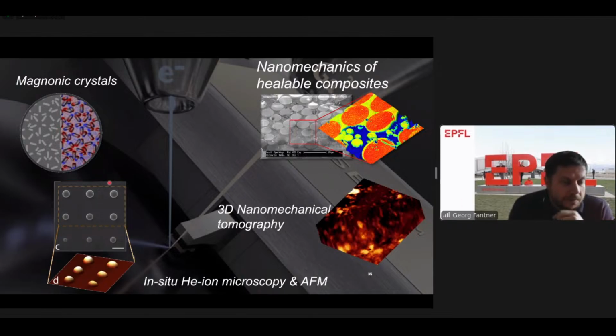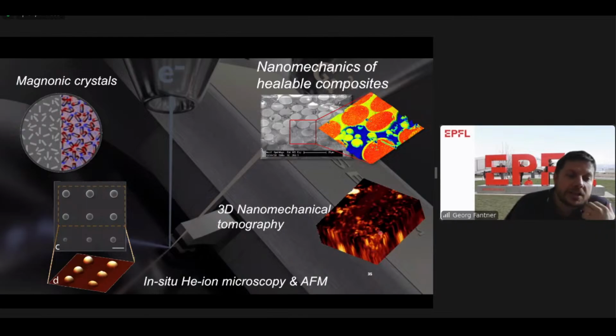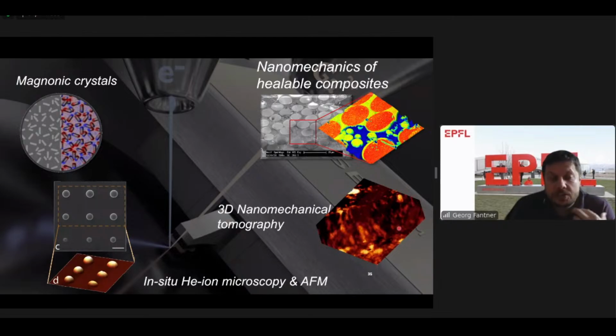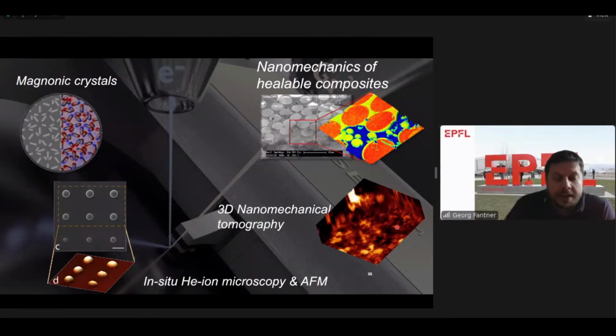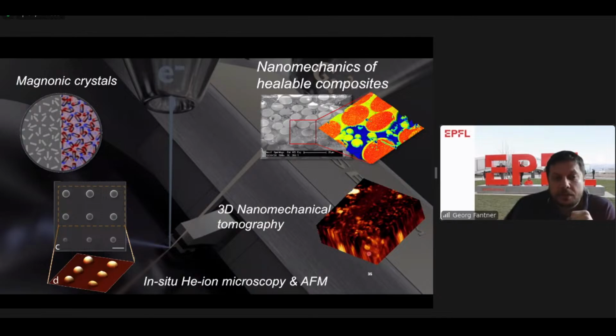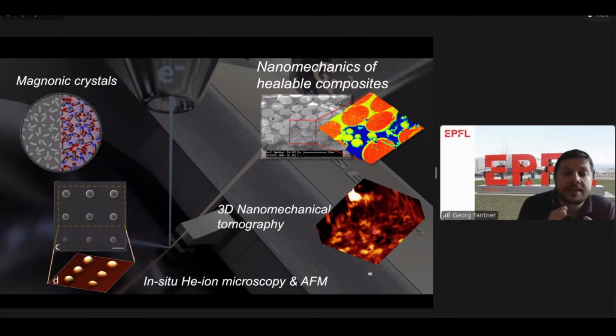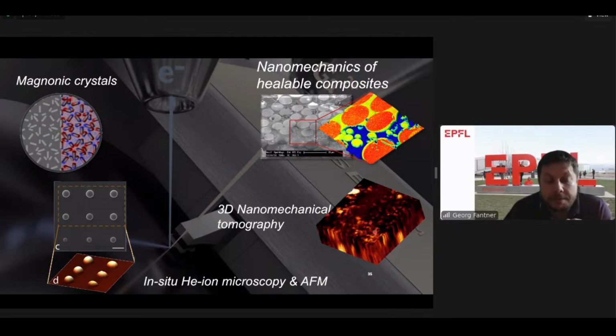And here, this is one of my favorite projects that we've done. We're looking at a piece of industrial rubber, which is a combination of rubber and carbon. As we're imaging, first we image the mechanical properties with the AFM, then we cut with the focused ion beam through the sample, and then we can reconstruct the 3D density map of the industrial rubber.